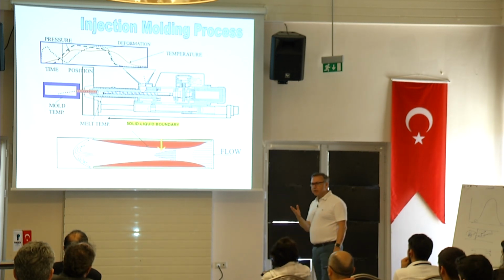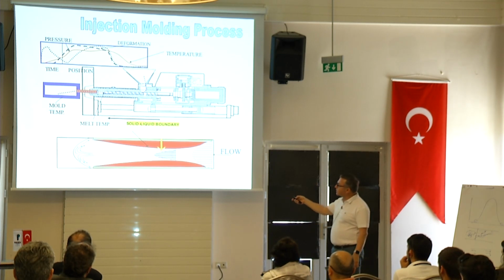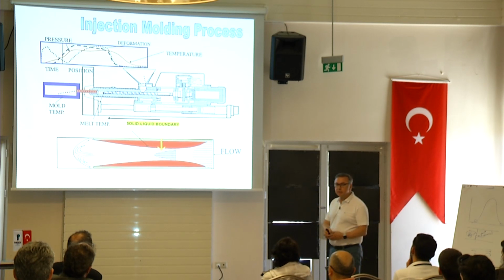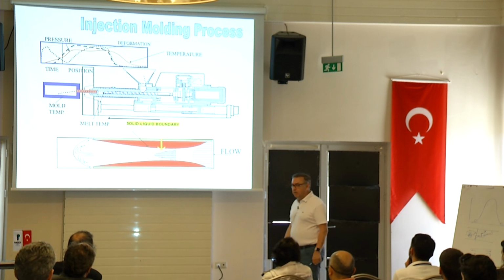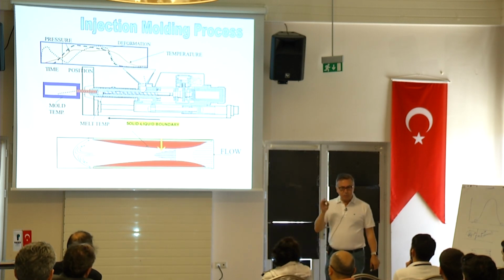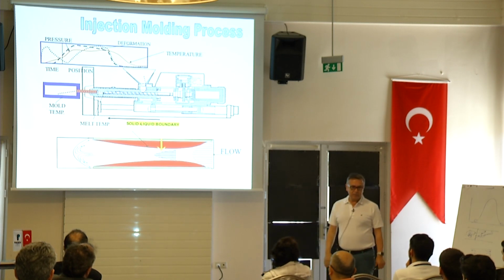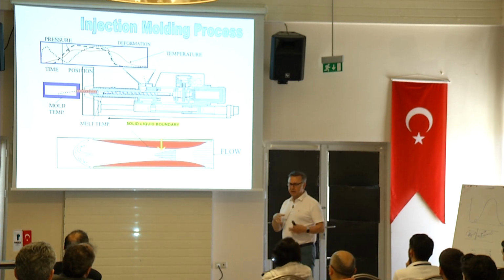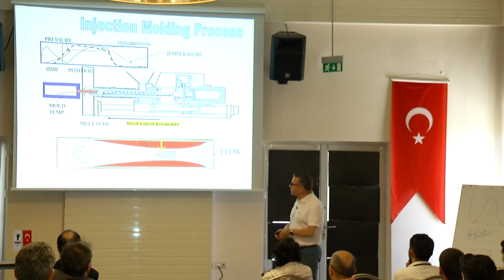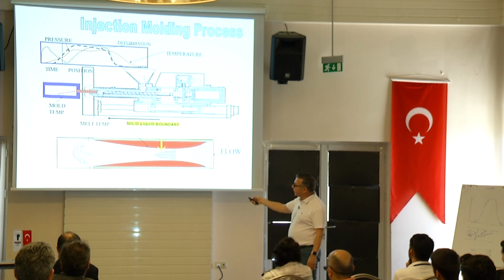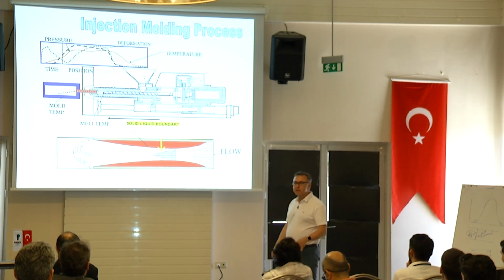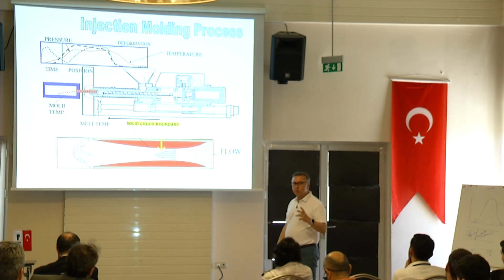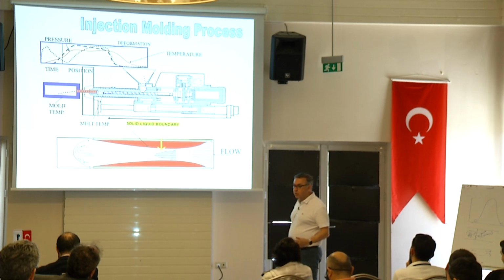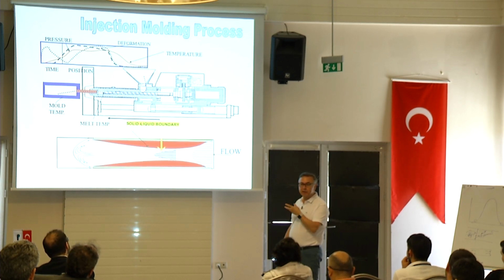I guess many of you have done injection molding. Have you ever seen a particle that has gone through the injection molding process without melting? I have. You have too, right? Our materials are such poor conductors that sometimes particles go through the whole machine without melting. Such a dramatic observation. Most people think that everything is homogeneous. Not so. Another consideration is whether the melt coming in is homogeneous. Is the temperature uniform within the melt itself? If you assume it is homogeneous, you're wrong most of the time, especially on big machines. Usually there is a temperature distribution, and as a result they put melt mixers on the machine, right? Tell me, you in the injection molding business, just to homogenize even the pure material without any blends.